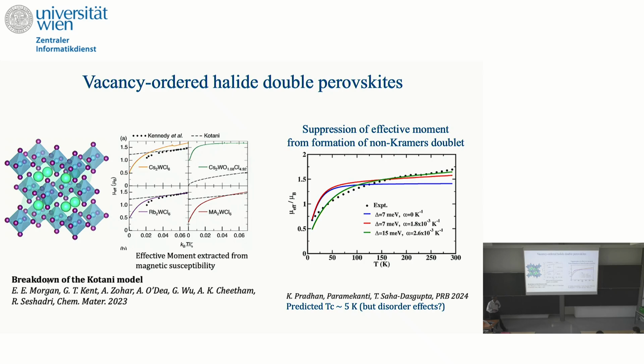that's been measured. So there are other systems other than the osmate double perovskites where we think this physics could be playing a role. But in these systems, the exchange interaction is actually weaker by about an order of magnitude. And so we predict that once they cool down to sufficiently low temperatures, they should probably see this ferro-octopolar order emerge even in these systems.